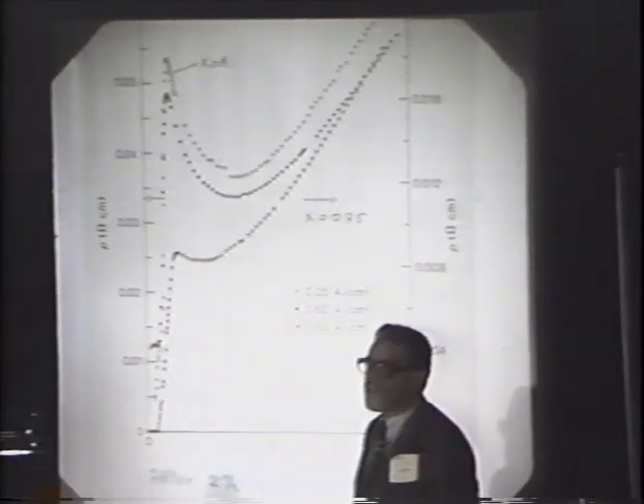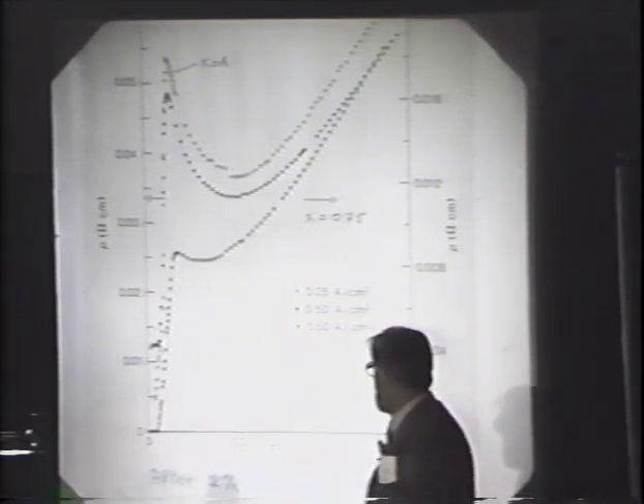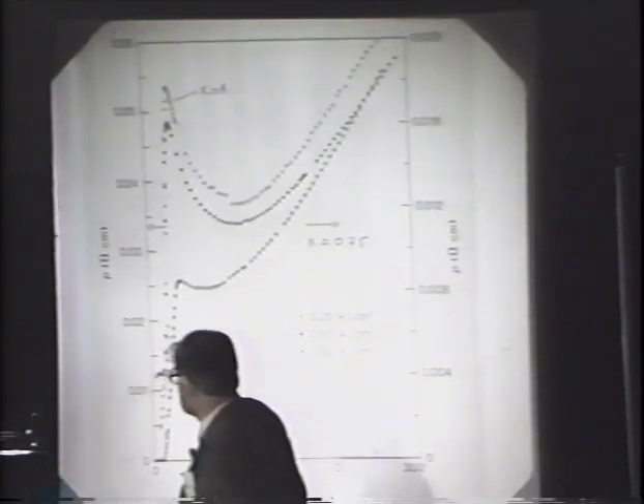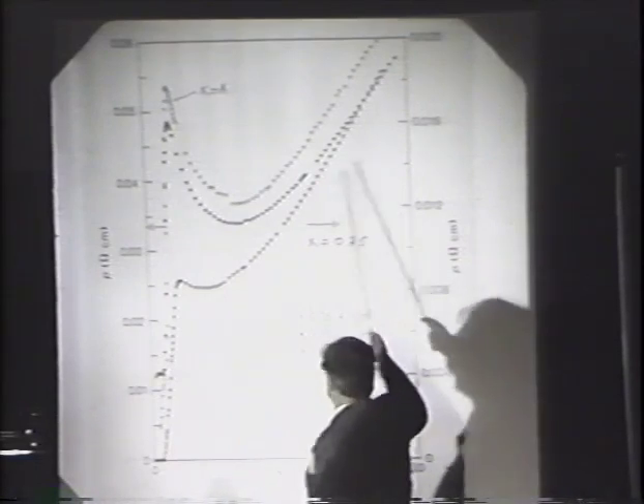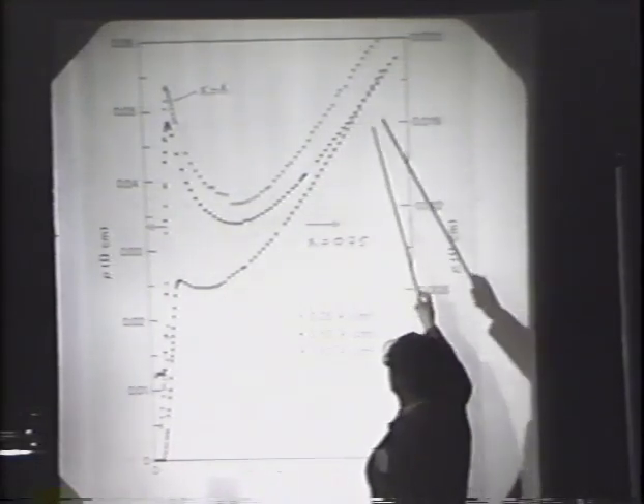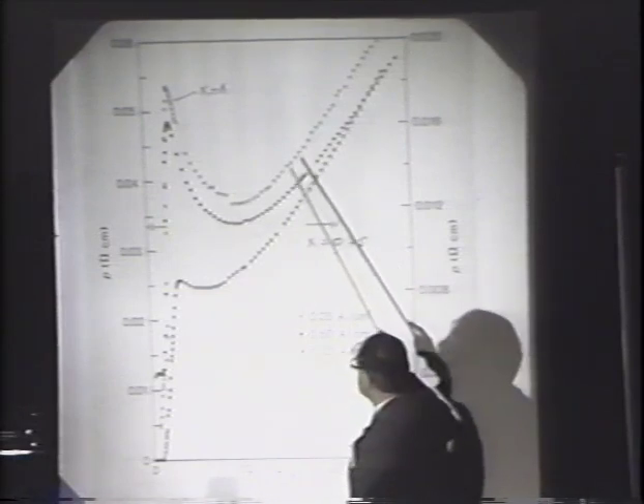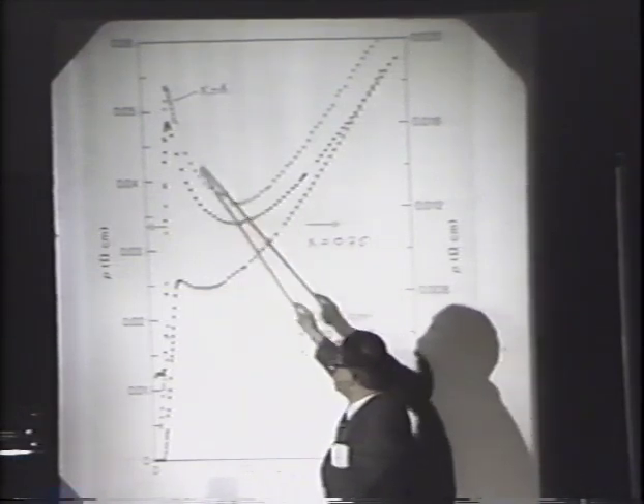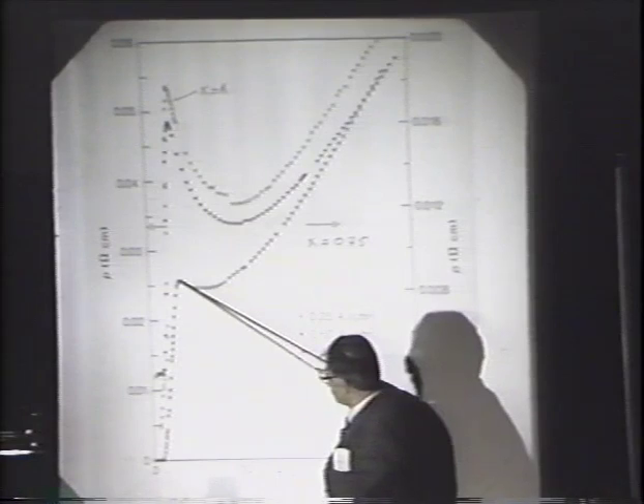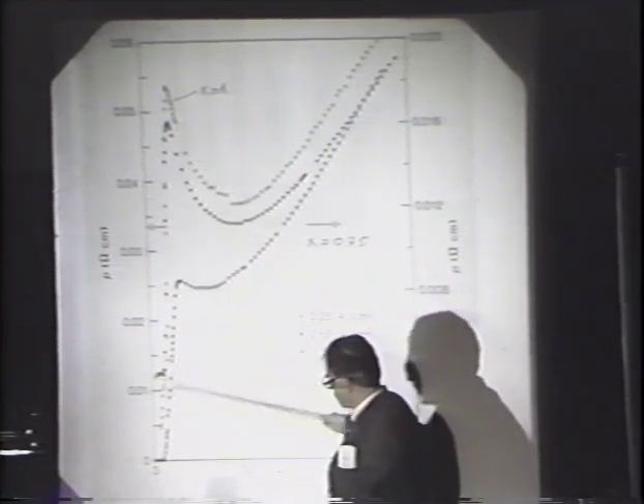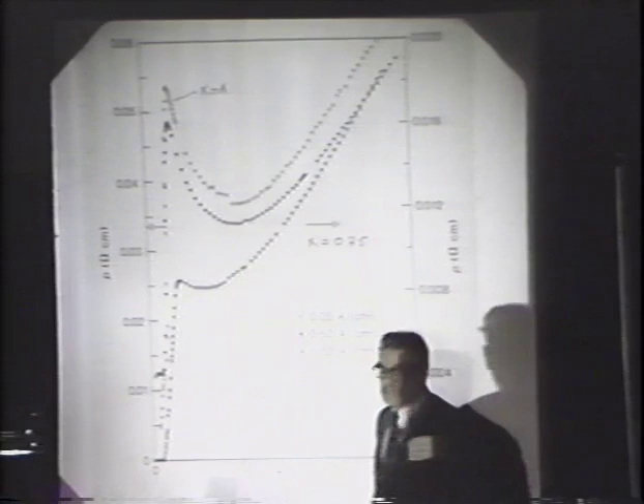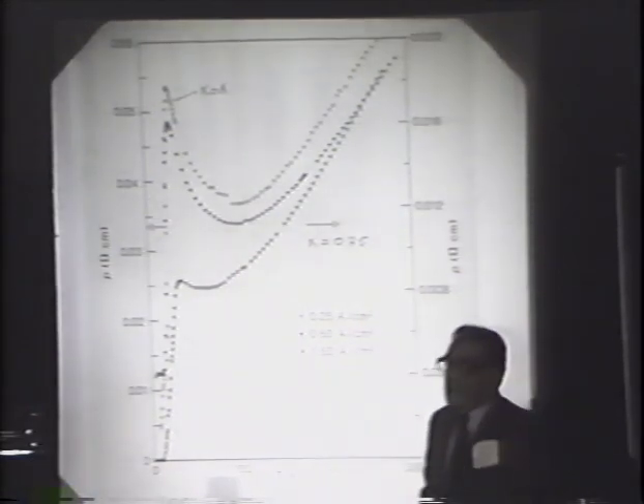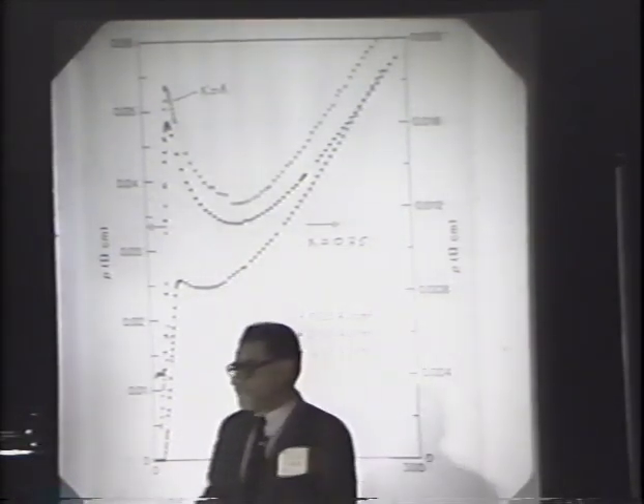It was strictly a two-man project, not even a technician was involved, it was George Bednorz and myself. And you see here that the resistivity as a function of temperature decreases metal-like, and then has a tendency to localize, and certainly you get the onset. And for example, for this sample, we couldn't measure, at least with our equipment, any resistivity anymore.